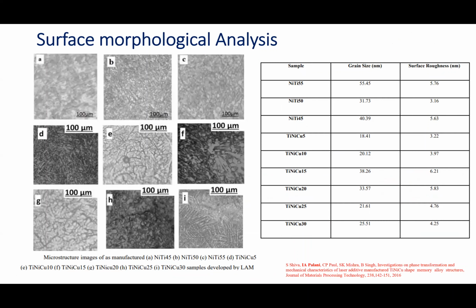As far as these structures are concerned, we did a microstructure analysis as well as an SEM analysis. Here we had the microstructure of TiNiCu samples developed by LAM in different compositions, and basically it provides a cross section of that sample. The samples were cold mounted and polished, and it shows a uniform TiNiCu microstructure, a dendritic microstructure which is due to the higher cooling rate.